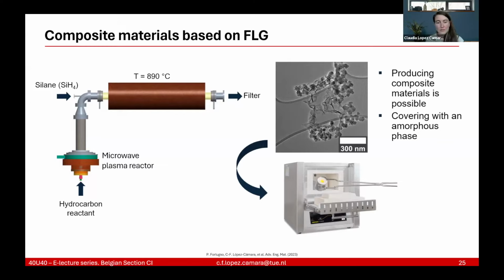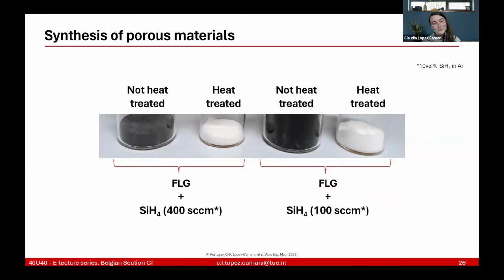And that was actually an unexpected observation, because my colleague put it in at night and it was black, and I took it in the morning and it was white. Evidently something happened. Therefore, we were shocked and we wanted to investigate it. As you can see here, there are 4 samples, but actually the 2 on the left are the same sample, 1 non-heat treated and 1 heat treated, and the 2 on the right, same thing.